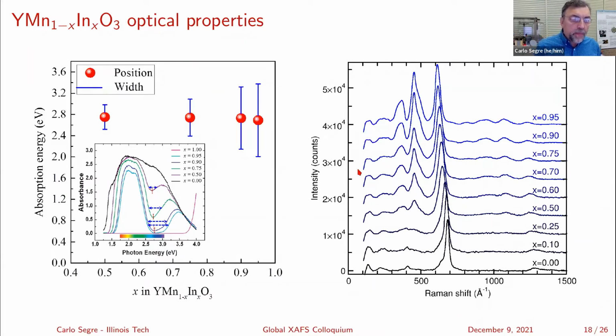And in fact, if we look back at the optical data, from the original paper in 2009, you can see that the centroid of this dip, which is the blue dip, is pretty much constant. It just gets broader and broader as you get to a smaller composition of manganese. We also took Raman data on these samples, and again, over here at x equals 0,